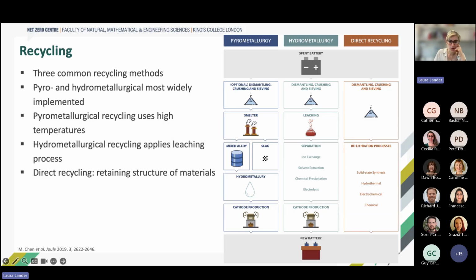The pyrometallurgical process uses as a first step very high temperatures to melt most of the components down, where we form on one side a slag, which contains some of the metals such as copper, aluminium, manganese, and also lithium actually, and we have the formation of this mixed alloy, which is then further treated via hydrometallurgical processes similar to the ones we saw here to extract cobalt, nickel, and manganese out of it. The direct recycling one is more straightforward.